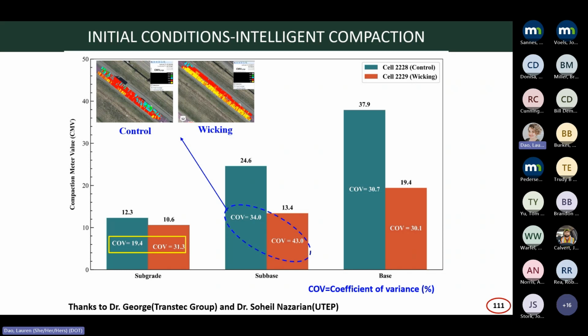These are the CMV values. And in the case of the wicking section, two different colors, yellow and red. So completely different values in the stiffness. That's actually contributing. And if we see the mean value of all these stiffness parameters in the subbase, there is a variation of 46% between the control and the wicking. Control was way higher, stiffer compared to the wicking section during the construction, during the initial conditions. So that's actually impacting the FWD results.